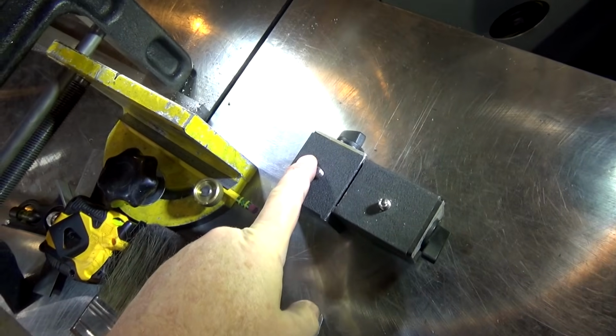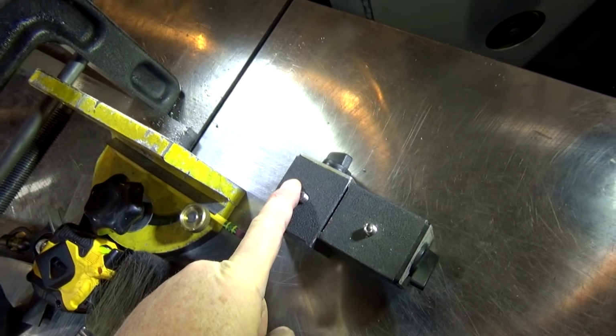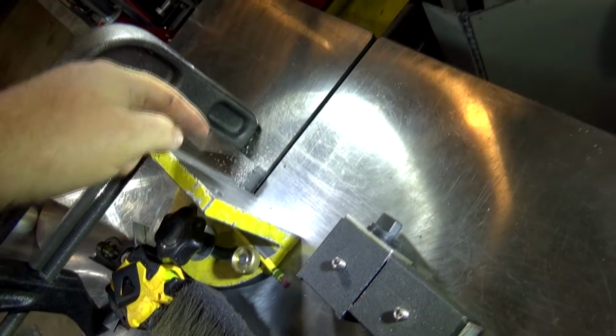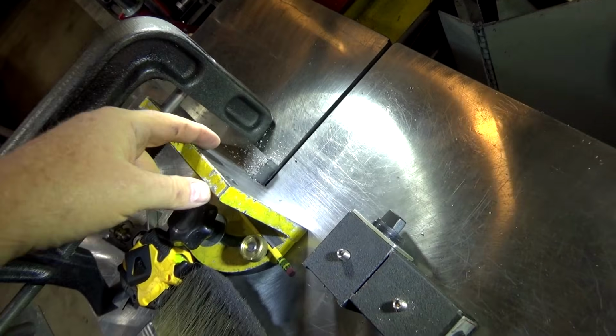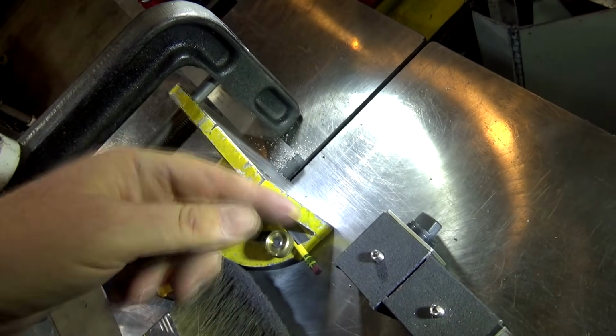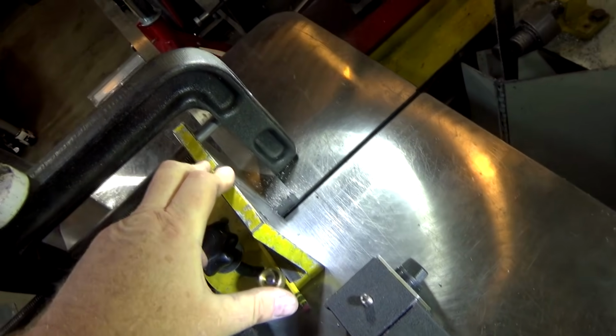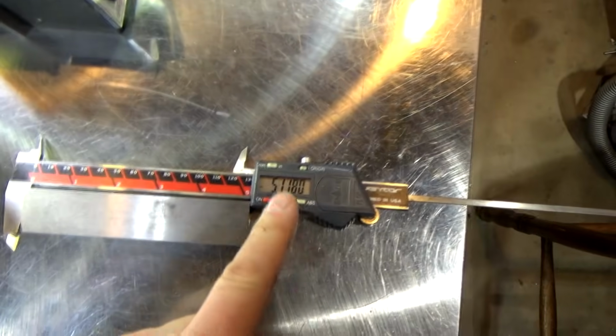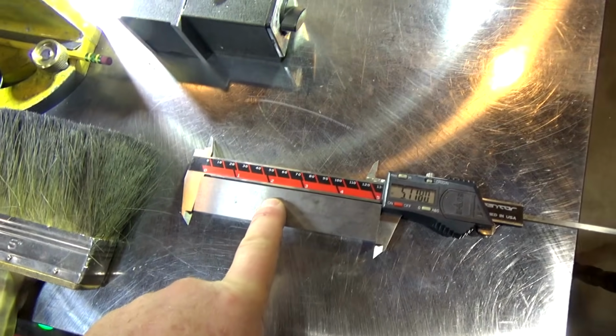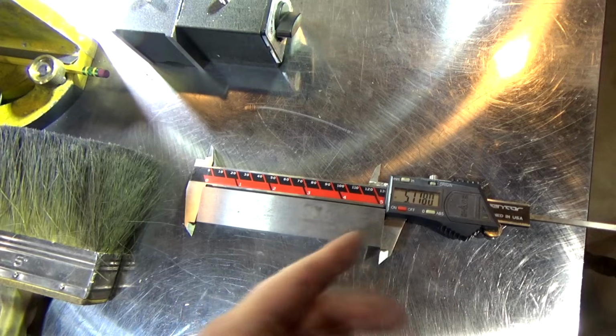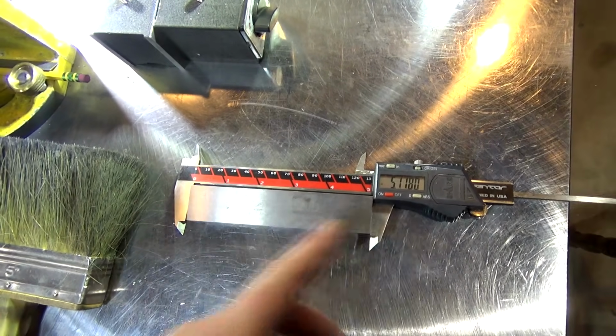I put magnetic stops here so that I could repeat these cuts more quickly, but you got to make sure to get all the swarf out of the way so that it doesn't screw up your thickness, especially when I'm as close to size as I am here. Measuring, I gave myself 5.118, so that leaves me roughly 43 thousandths, so 20 thousandths aside to remove, which should be fine, hopefully.